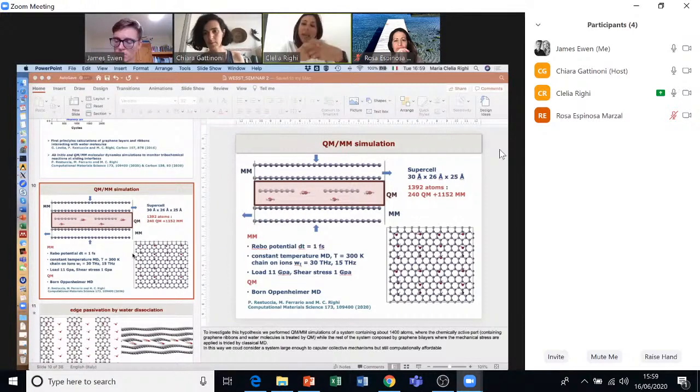And in one case, graphene flakes were passivated with hydrogens, and in the other case were not. So in the case when no passivating species are present, these flakes form chemical bonds with the 2 surfaces and the system was stuck.